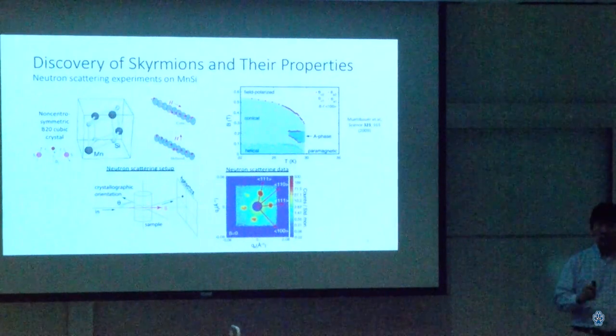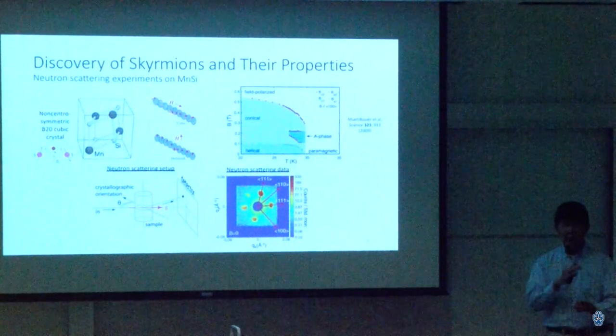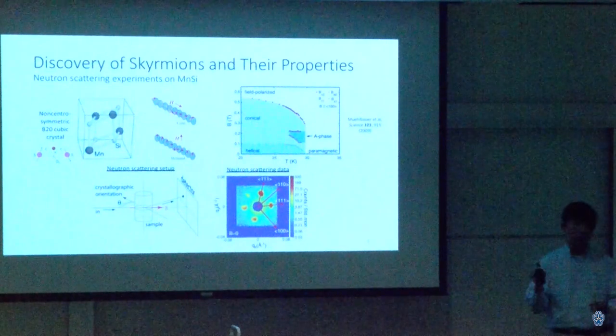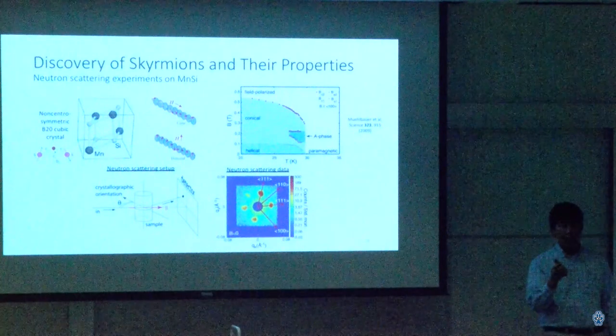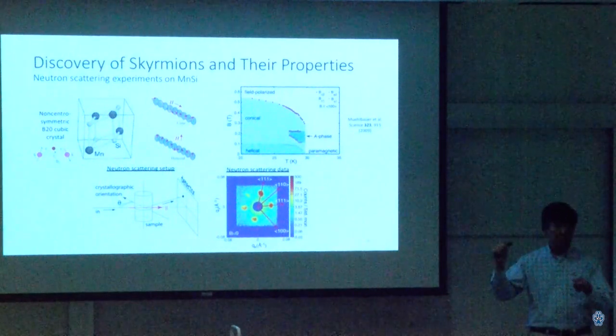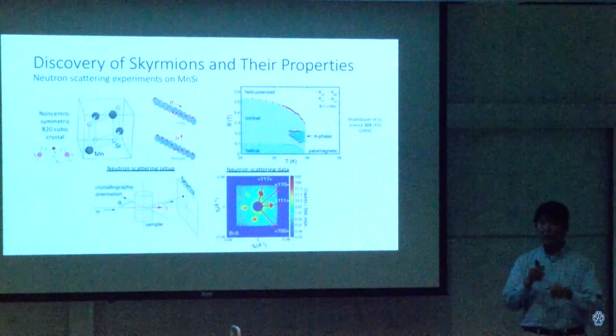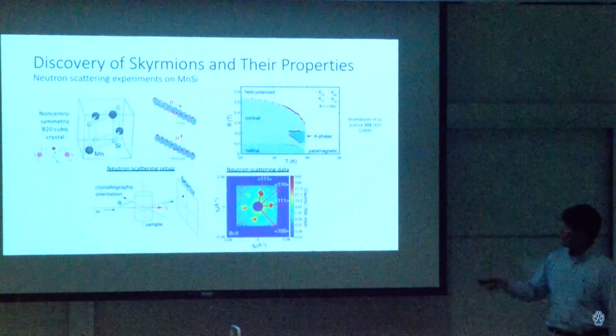And the reason why neutrons were so interesting to them is because neutrons don't have an electrical charge, so they won't interact with the electrical charge of the electrons or the nuclei. On the other hand, neutrons have a small magnetic moment attached to them. So they'll, via dipole interactions, interact with the magnetic moment of the electrons in this material. And then it'll give you a pattern like this.